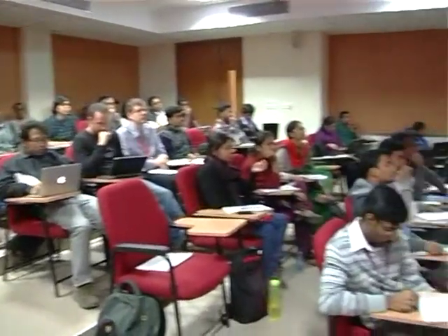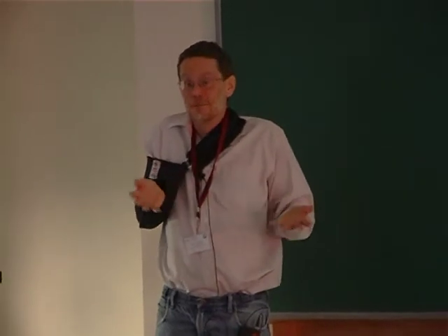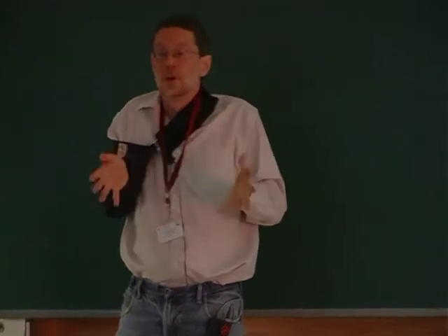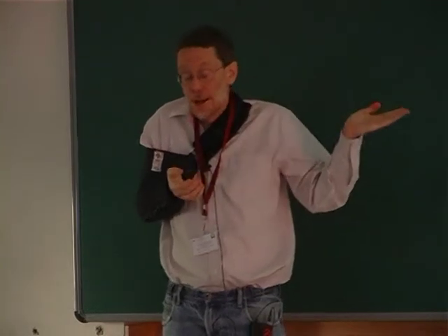Yes, I would agree with that statement. I would put it slightly differently. We know, and I didn't have time and space to put it in this talk, that DFT in all its incarnations has troubles with excited states. It doesn't get them correct. And this energy mismatch of about a volt is well within the reasonable range of DFT error. So you have to fix it up somehow. And the question is, what's the right way to do it? I agree that GW is maybe a promising way to think about it. My colleague Marianetti says that the right way to fix it up is this double counting correction, because all you really care about is a relative splitting between two bands. Maybe it's theological, maybe not. I think that's an issue where we have to do more.